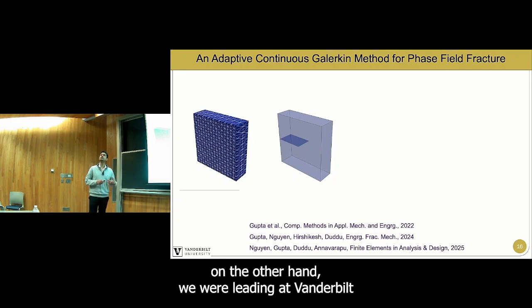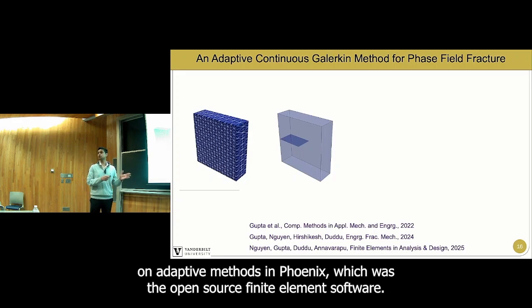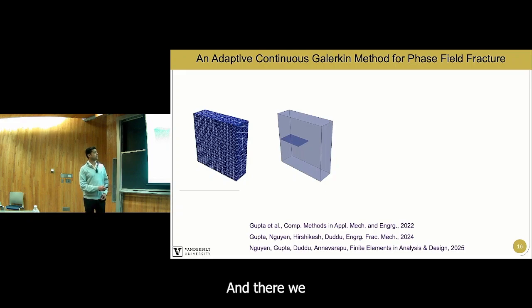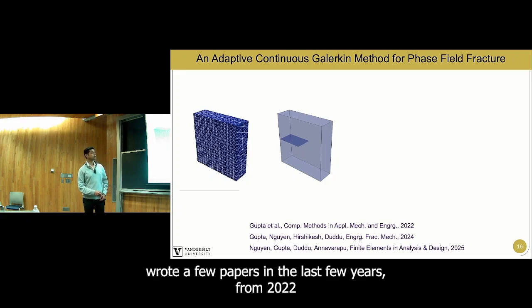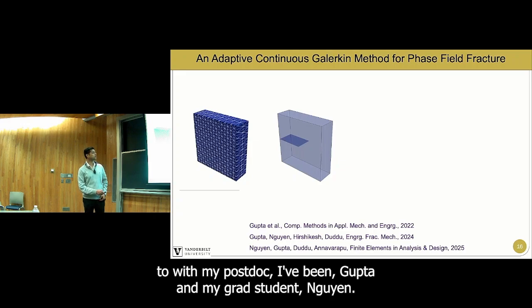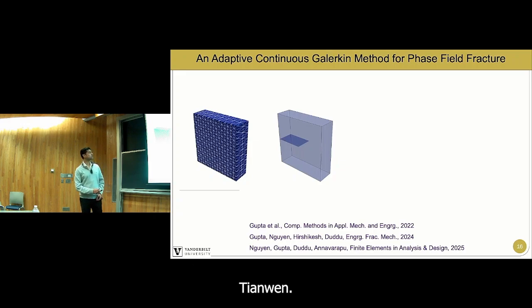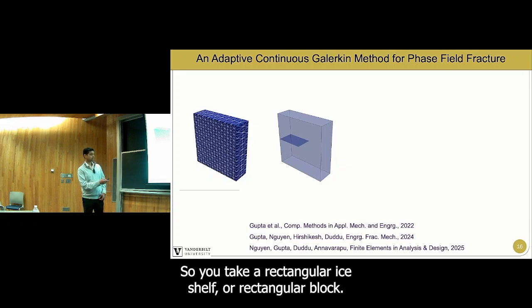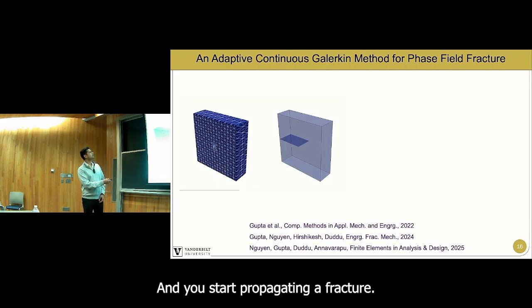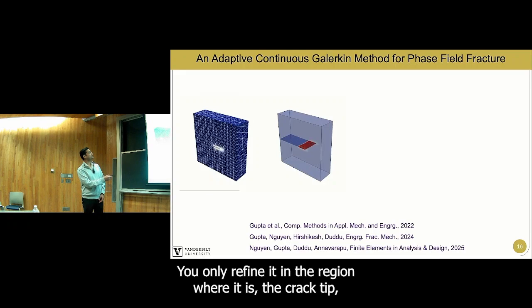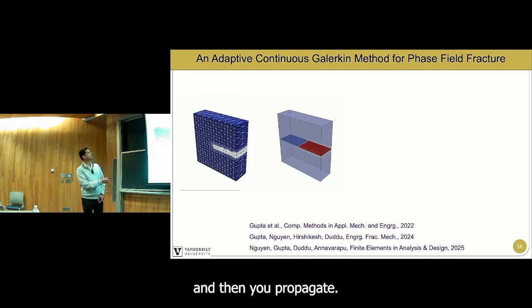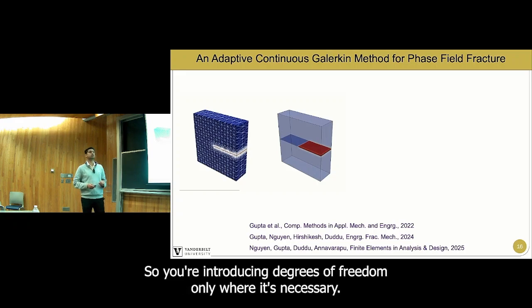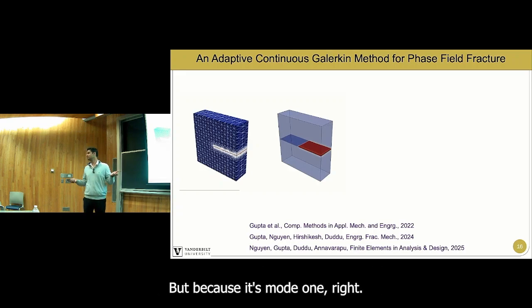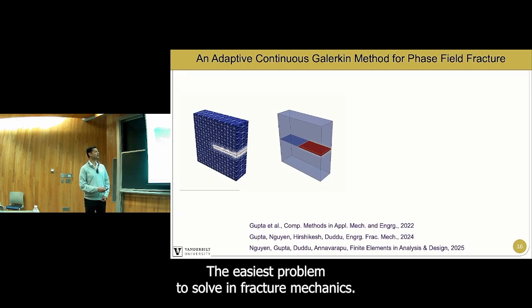On the other hand, we were leading at Vanderbilt on adaptive methods in FEniCS, which is the open source finite element software. And there, we wrote a few papers in the last few years from 2022 with my postdoc, Abhinav Gupta, and my grad student, T.N. Nguyen. And this is how it works. You take a rectangular ice shelf or rectangular block, doesn't matter, and you start propagating a fracture. You only refine it in the region where it is the crack tip, and then you propagate. You didn't refine anything in the far field, so you're introducing degrees of freedom only where it's necessary. And you get a very nice fracture path because it's mode 1, right? The easiest problem to solve in fracture mechanics.